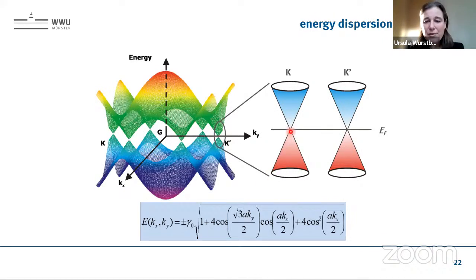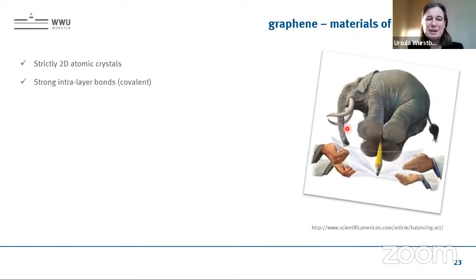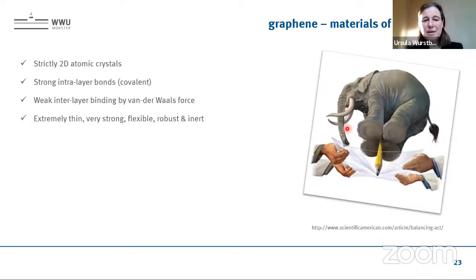And also we have here a touching point, meaning the occupied valence band states touch the conduction band states at one joint state here, and with that you can continuously tune from hole to electron conductivity. Well, there are a lot more fascinating properties for graphene, like it's a strictly two-dimensional atomic crystal. We have strong covalent intralayer bonds, and weak interlayer binding by van der Waals force. It's very thin, very strong, flexible, robust, and inert.